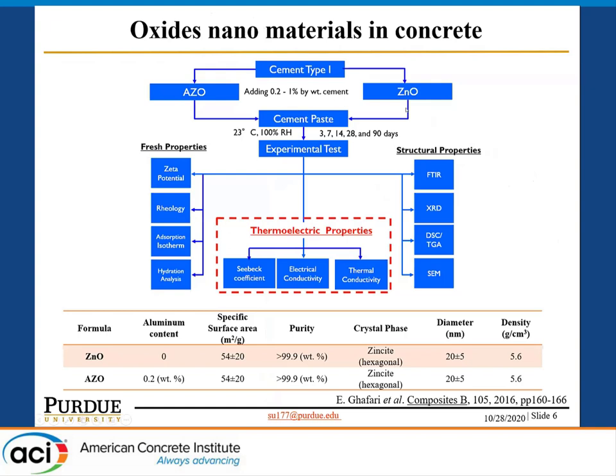And this is one of our studies using oxide nanomaterials in concrete. We use two different oxide materials, zinc oxide and aluminum-doped zinc oxide, to blend with type 1 cement, and the addition rate is from 0.2 to 1% by weight of cement. We did a series of experimental tests for the thermoelectric property evaluation, like the Seebeck coefficient, electrical conductivity, and thermal conductivity.